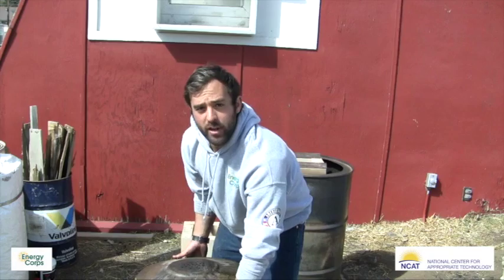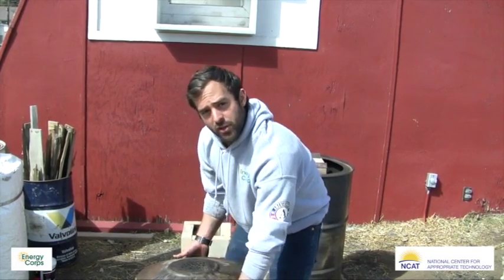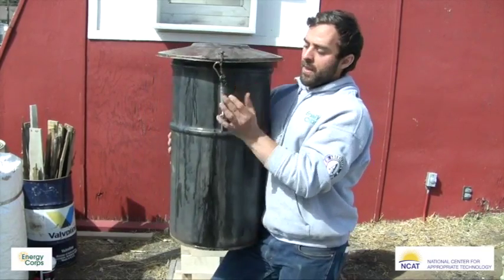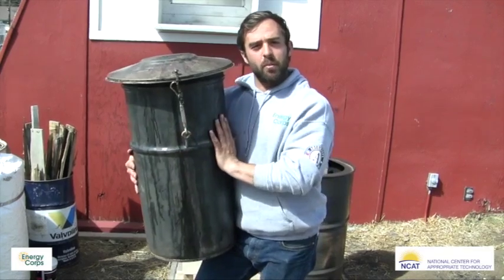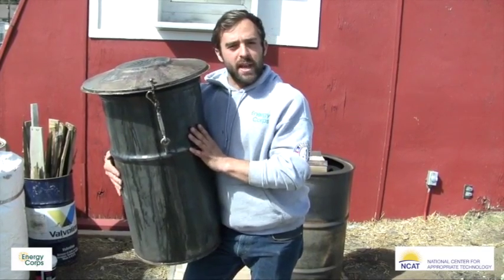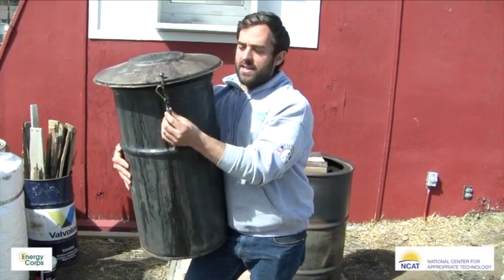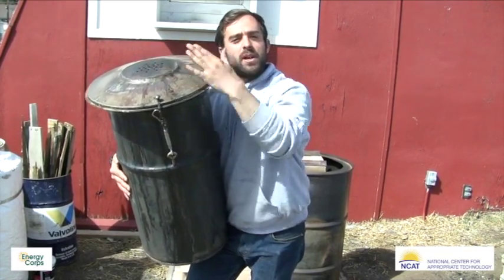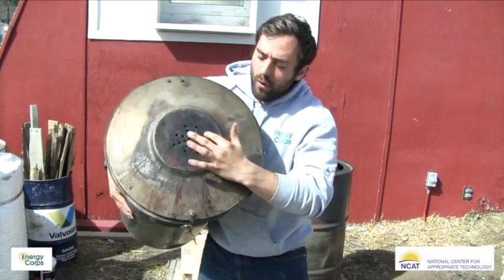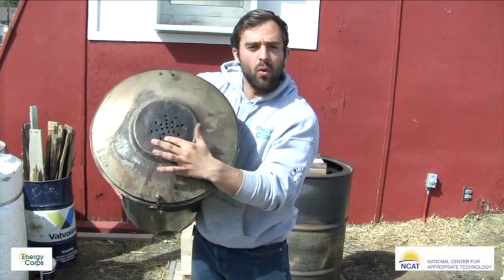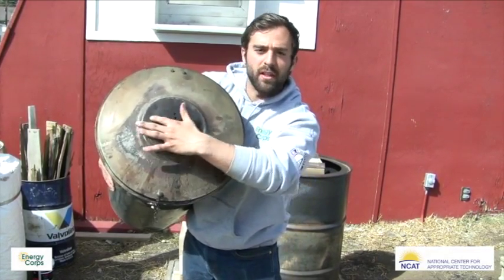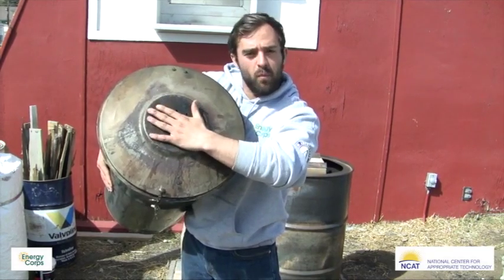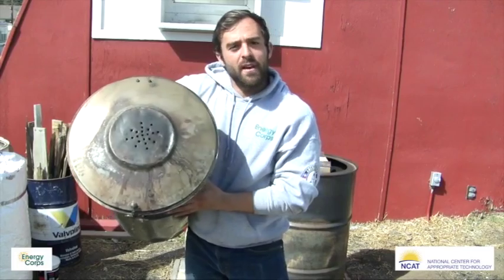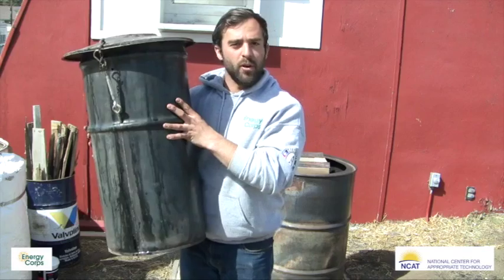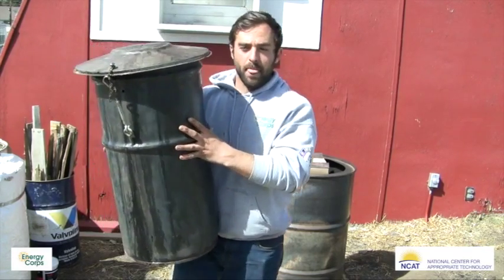So once your biomass is loaded inside the retort, you want to make sure the lid is nice and snug. But whenever this material begins to get hot, it is going to start letting off wood gases, and you need a place for those wood gases to escape. So as you can see, this lid is nice and snug on here, but I still need a place for the gases to escape. So in our case, we've drilled 24 quarter-inch holes in this portion of the lid. And this allows the wood gas to escape. If you didn't have a place for the wood gas to escape, this barrel would build up pressure and would probably bulge and